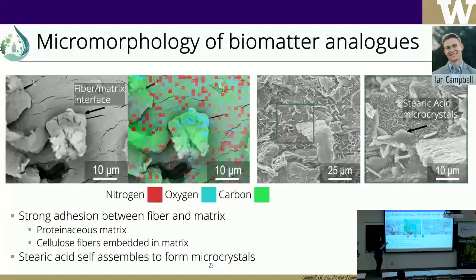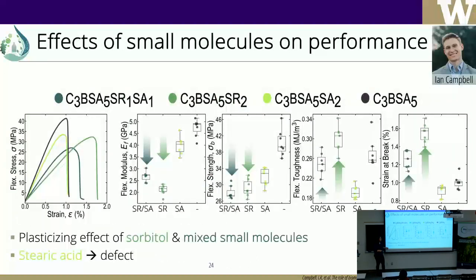So our simplified system allows us to see that in this combination of materials, protein is playing the role of a matrix. Your cellulose fiber is going to be your structural fiber there, and we're going to see it in mechanical properties as well. They're going to be embedded in the matrix. These are going to be very hydrogen bonding prone interactions. They are designed actually for that, so of course they're going to interact very nicely. You won't see bad interfaces around these two. And then we did see the fatty acid assembling into microcrystals and migrating all the way to the surface.